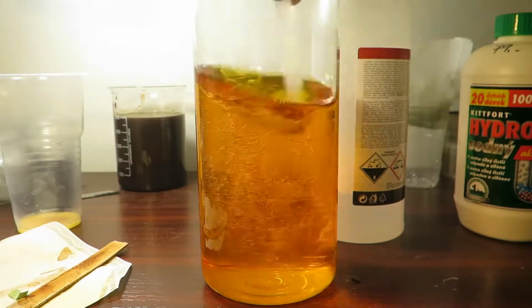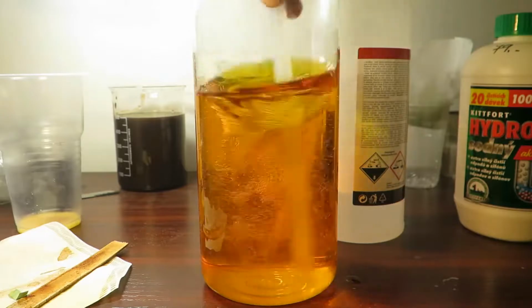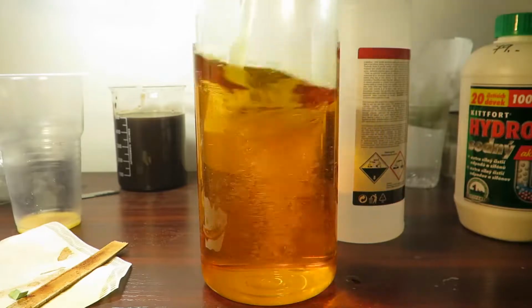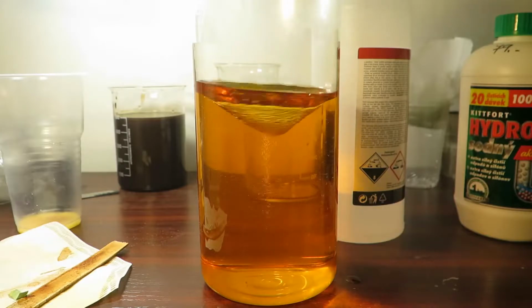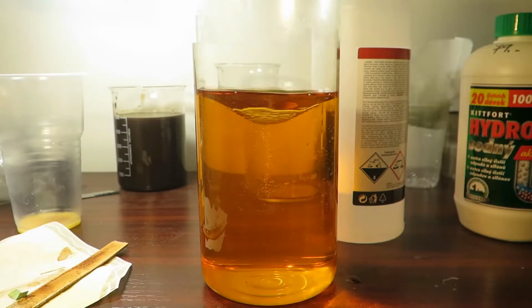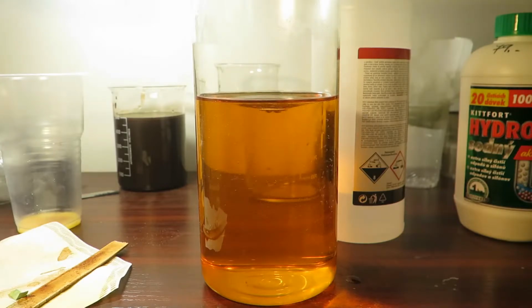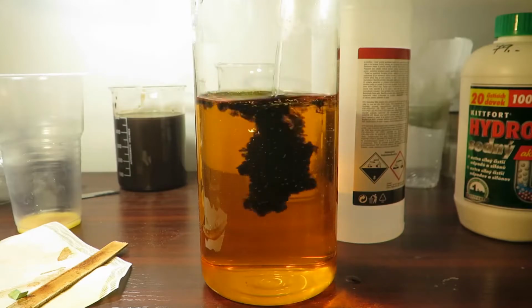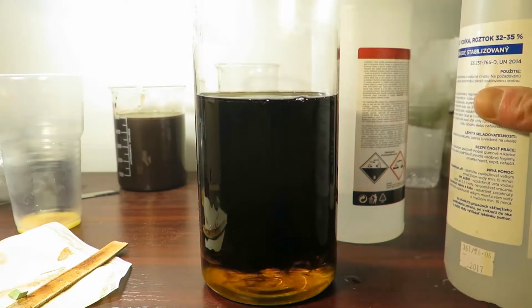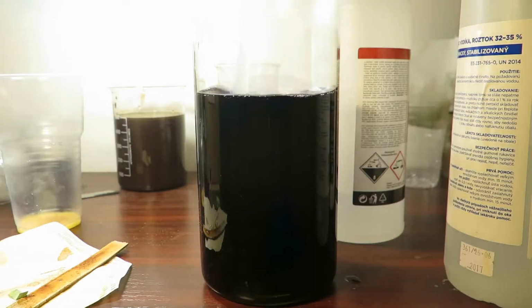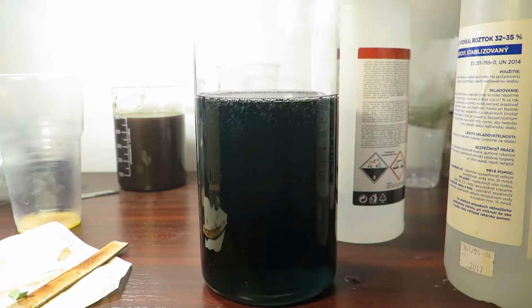Then you can add hydrogen peroxide to the solution, and finally we can oxidize this even more to the oxidation state +7. Chromium in this oxidation state is not stable in water solutions, and conveniently it will reduce itself to the oxidation state +3. This is the way to go, because otherwise you will have to boil away the hydrogen peroxide that's remaining there. I don't really understand how it can persist there, because it is supposed to oxidize the chromium, but I guess magic? Anyway, let's proceed. Immediately after addition of hydrogen peroxide, the solution will change color from orange to, well, some darkish violet blue, and then transition slowly to green.